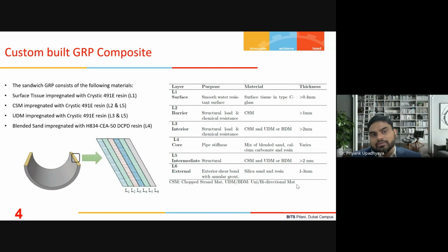So what we are doing in this project is using a custom-built GRP composite, which has 6 layers, and each layer has its own purpose. Internally, the first layer is the L1 layer, which is a smooth water resistance layer, so that the water or the sewage flows smoothly inside. This is approximately 0.5 mm, and is made from glass fiber surface tissues. The next layer is called the barrier layer, which is for structural load as well as chemical resistance. This is made of chopped strand mat, and its thickness is approximately more than 1 millimeter.